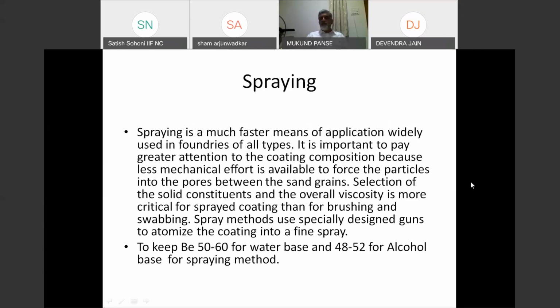The next method of applying coating is spraying. Spraying is a much faster method of application used in foundries. The care you have to take is that you get uniform air pressure so that the coat is uniform. You also see that the air you get is completely moisture free. The permeability of the coat should be good enough so that air entrapment is not there.